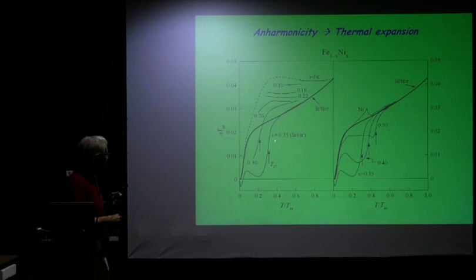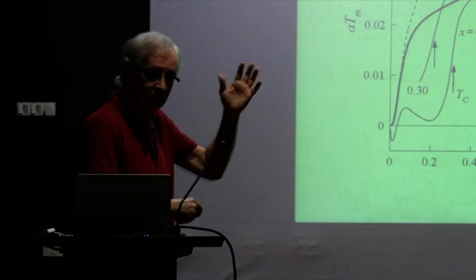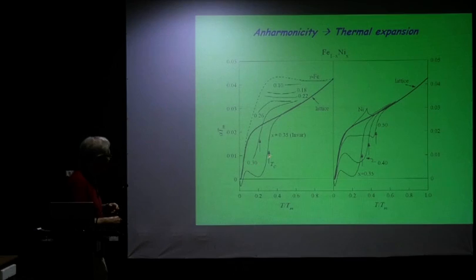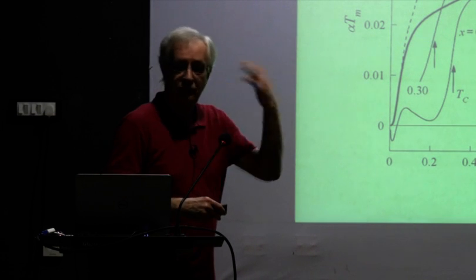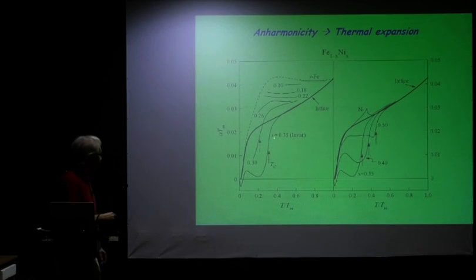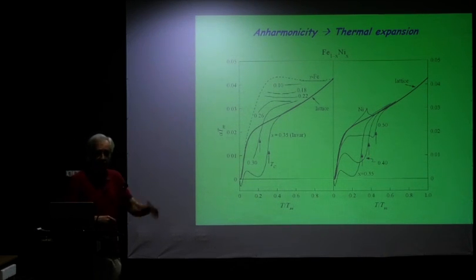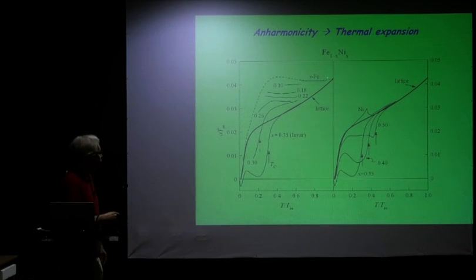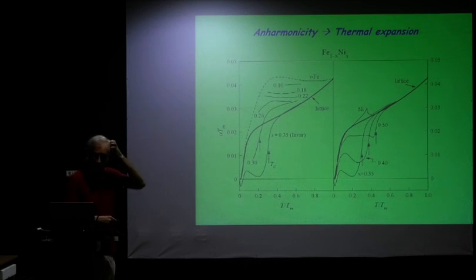And then you come here to the INVAR composition, where the room temperature thermal expansion coefficient was 0, what Guillaume had measured, and you find that at high temperatures it conforms to the general lattice expansion, but when you go down in temperature, it suddenly does something funny, and it deviates from this general lattice expansion property. So these deviate positively, and these here, they deviate negatively.